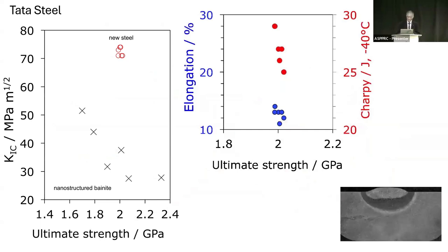And look at the properties, okay? So untempered high carbon martensite, we can get at minus 40 degrees centigrade, Charpy toughness of that much, and elongations which are respectable, and a strength level of 2 gigapascals produced on a rolling mill. And this is work we did a long time ago on nanostructured bainite, and we beat that, I'm afraid to say, okay? Bainite is my favorite subject, but we have beaten that. We can consistently produce a toughness of 75 megapascal root meters at a strength of 2 gigapascals in this steel, and we can weld it using arc welding.